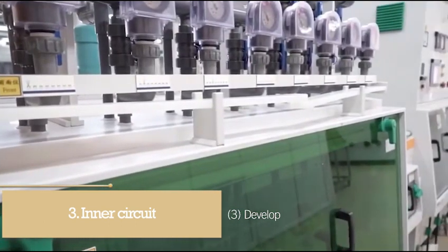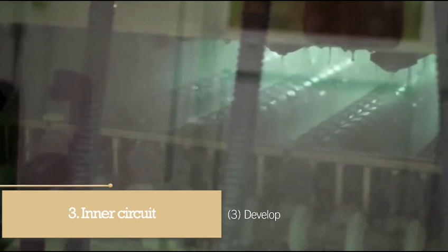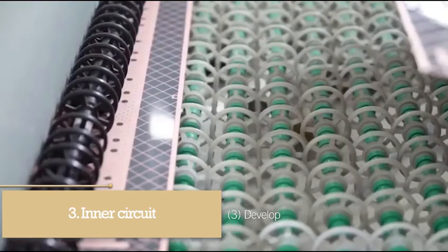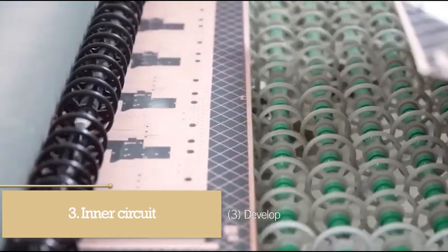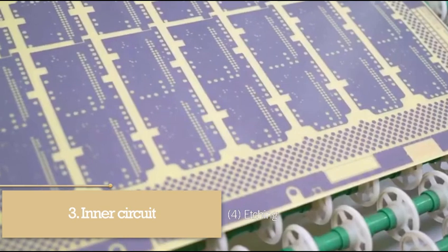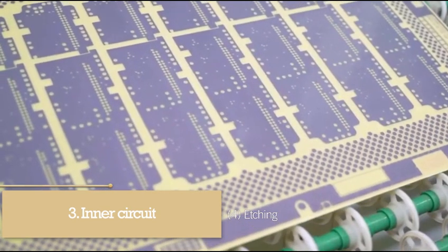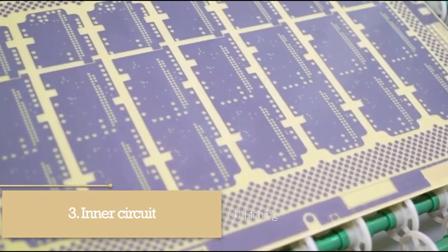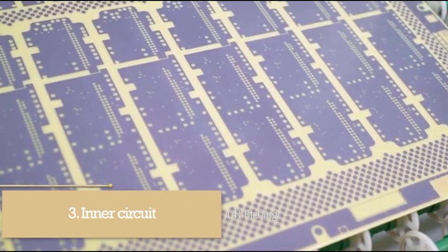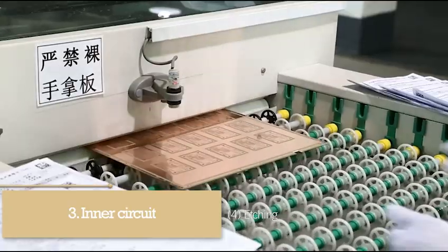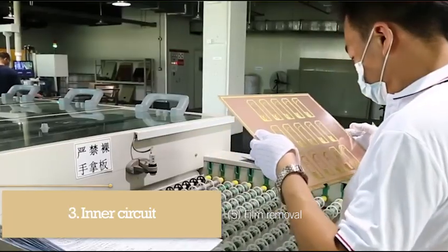3. Develop. Using the weak alkalinity of the developer, sodium carbonate, the unexposed dry film is dissolved and washed away, leaving the exposed part for etching. 4. Etching. After the unexposed dry film is removed by the developer, the copper surface will be exposed. Use a hydrochloric acid mixed solution to dissolve and corrode this part of the exposed copper surface to obtain the required circuit. 5. Film removal.